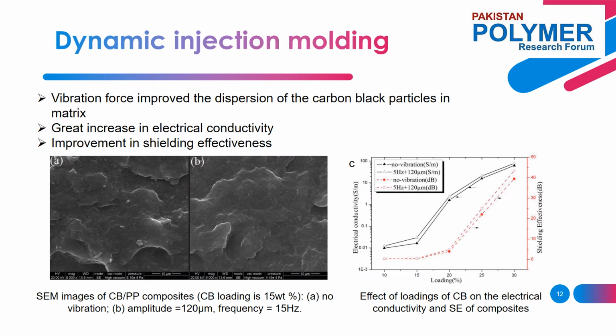Morphological analysis was performed to study the effect of vibration force on the dispersion and distribution of the carbon black nanofiller. Micrographs from SEM analysis are shown in figures A and B. Figure A shows the micrograph of the carbon black and polypropylene nanocomposite without any application of vibration force. It can be seen that the distance between carbon black nanoparticles is large with no vibration, and the carbon black particles have no obvious agglomeration in the matrix. The density of particle distribution is not big enough for the formation of a conductive network, because particles can aggregate easily in the molding process.